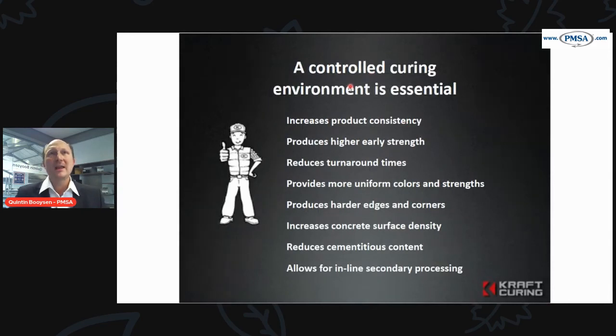A controlled curing environment is essential for increased product consistency, produces higher early strengths, meaning you can strip quicker or you can get your board back quicker, which means reduced turnaround times, provides more uniform colors and strength, and produces harder edges on your concrete. We spoke earlier that 30, 40 millimeter area on the outside: if we can really get good curing from the start, we get sharper edges, stronger edges, which means more durable concrete. Increased concrete surface density and reduced cement content, and allows for inline secondary processes.